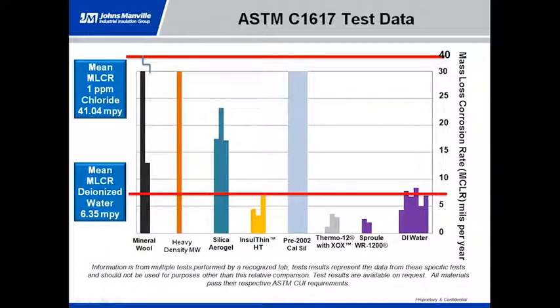So what happens when we get done is that we have a kind of a ranking here. Going from left to right, mineral wool, and even jumping in the middle to the pre-2002 calcium silicate, you have pretty high corrosion rates. Silica aerogel is a little bit better. You look at InsulThin HT and DI water, they're about the same. And then you have the Thermo-12 with XOX and the Sproule WR-1200 products, which are below DI water. So what this means in terms of corrosion, if you look at the boxes on the left-hand side, is your deionized water has a mass loss corrosion rate of about 6.4 mils per year.